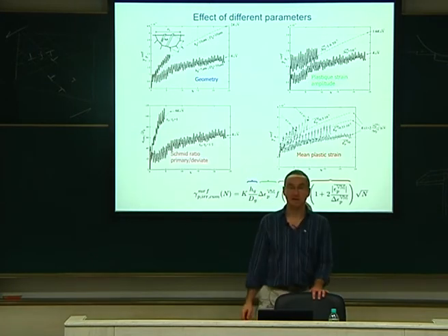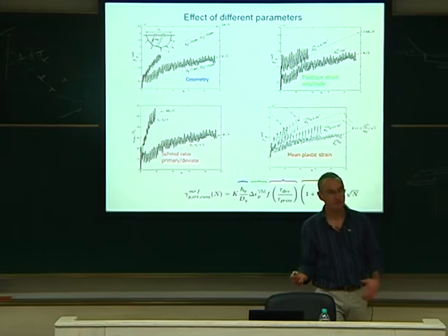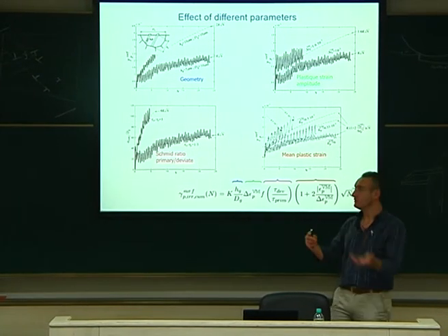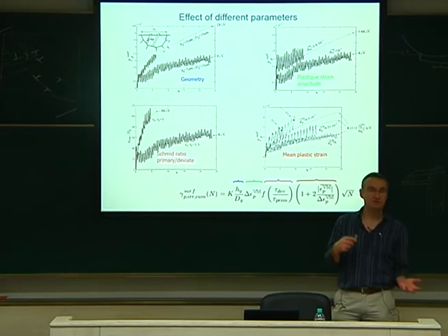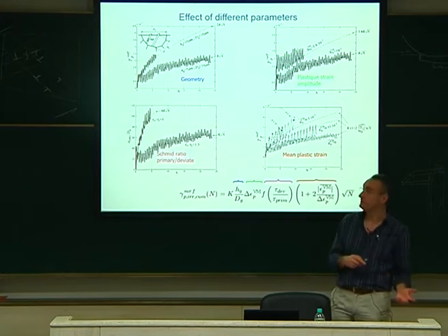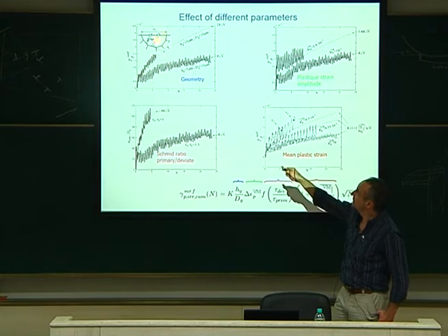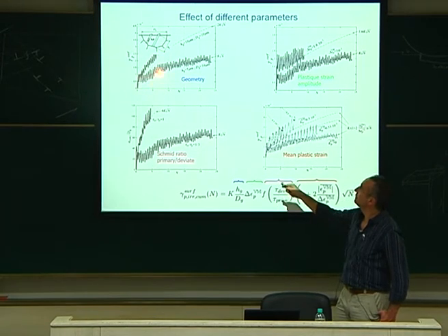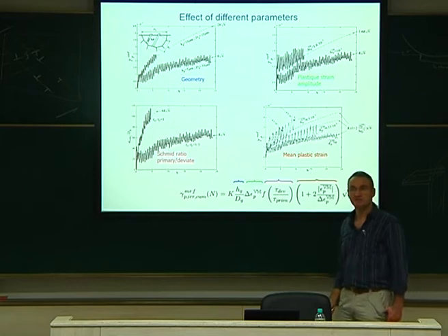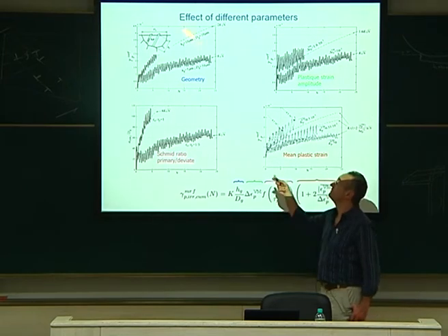And now that we have this in hand, we can change many parameters, make a new parametric study, change everything, and see which is good for the material and which is bad. So, for example, if we take 2 grain shapes, here we just change the height of the grain along the Burgers vector. So we take something deep or something short. If it's short, h is equal to 5 micron. If you double that size and put 10 micron, you have something which is more irreversible. It means that it is bad for the material to have something deep.